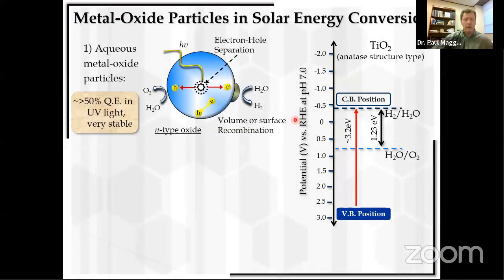Now, this has become quite a popular field, and for the capture and conversion of solar energy, there are 2 primary formats, at least to do this heterogeneously. One is in the form of metal oxide particles, which have been very efficient, at least in the ultraviolet. How metal oxides work to convert sunlight into chemical fuels is by their absorption through band gap irradiation, the creation of electron hole pairs within the particle, and then those electron hole pairs must be separated and then drive either water reduction and or water oxidation at their surfaces.